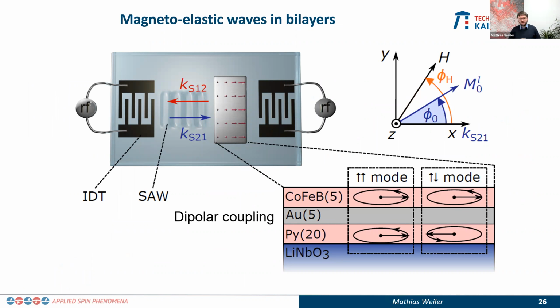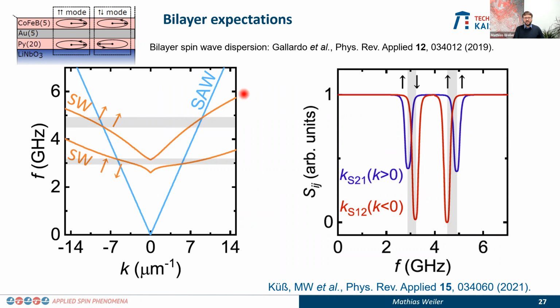So then, we thought about other ways to increase the spin wave non-reciprocity further. And one can, instead of relying on Dzyaloshinskii-Moriya interaction, rely on classical dipolar interactions. So it is very well known that in dipolarly coupled bilayers of ferromagnetic thin films, and here we take permalloy, cobalt iron boron, and the gold is only here to prevent exchange coupling between the cobalt iron boron and the permalloy. And in such layers, it is very well known that the spin wave dispersion shown here becomes highly non-reciprocal. There is a complication because you have these two ferromagnetic layers, and that is you get an acoustic and then optical mode of the spin waves here. But as you can see here, both of them are actually non-reciprocal, right? So here you end up at 4 gigahertz, and here you end up somewhere below 4. Same for the acoustic mode. Okay?